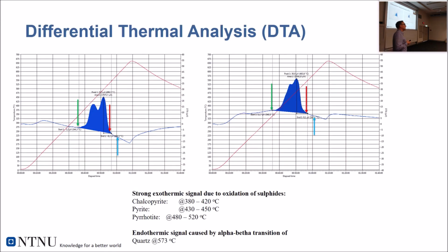We also tried differential thermal analysis of the same material to see if that could be more precise. This is a method that is recommended by the standards. Differential thermal analysis utilizes the temperature, endothermic and exothermic reactions that happen when pyrrhotite or sulfides are oxidized during heat. So you heat the samples to 700 degrees and measure the thermal response during heating. In literature, chalcopyrite has reactions at about 380 to 420 degrees, pyrite at 430, and pyrrhotite at 480 to 520. I also mention quartz because the alpha-beta transition of quartz is used to check the temperature readings.